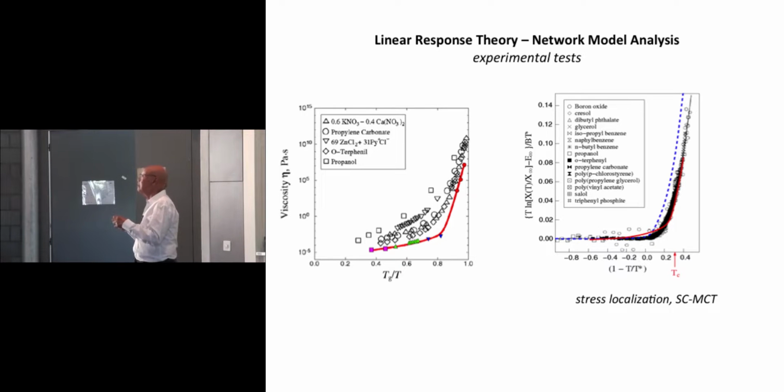That long wait means that the local shear stress is localized. When the shear stress is localized, that implies physically the stress-stress autocorrelation function doesn't decay very fast. And that's the reason why the viscosity is going through the roof. The correlation function has a very slow decay. And when that happens in diffusivity, you call that structural arrest, and the diffusion coefficient goes to 0. Viscosity becomes very, very large.